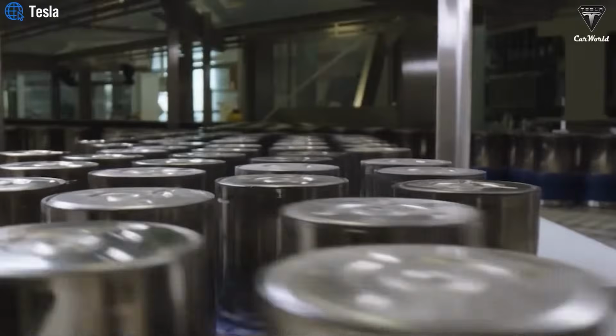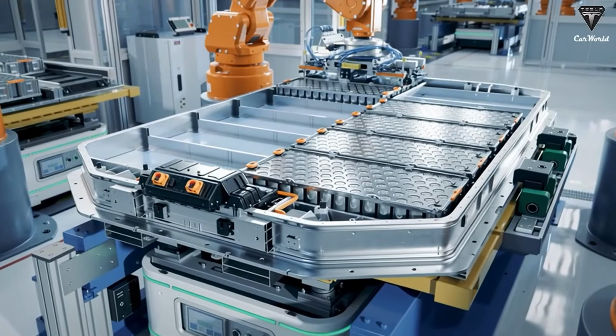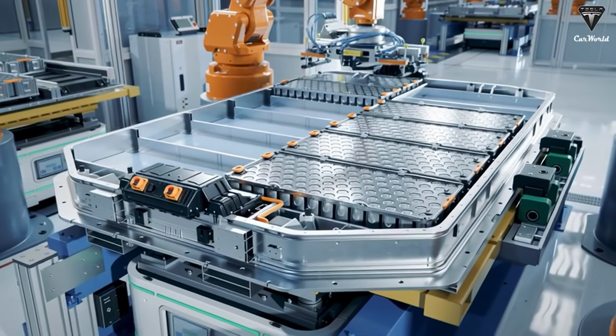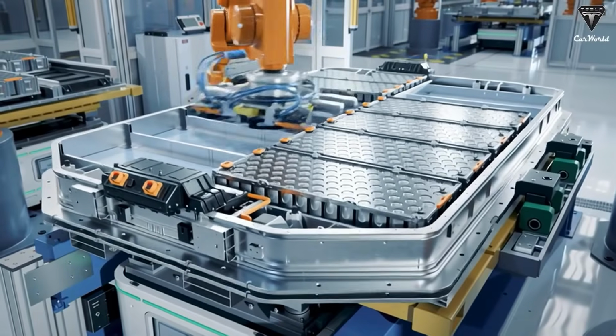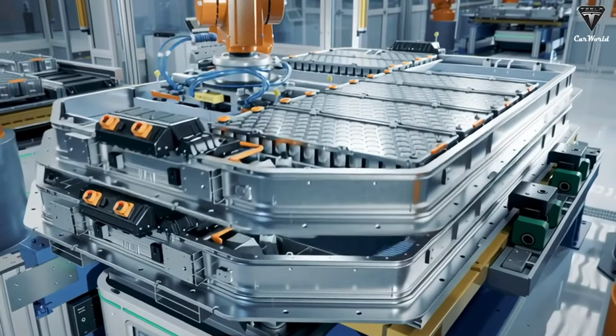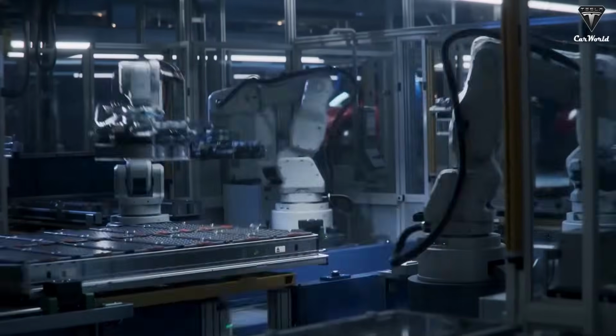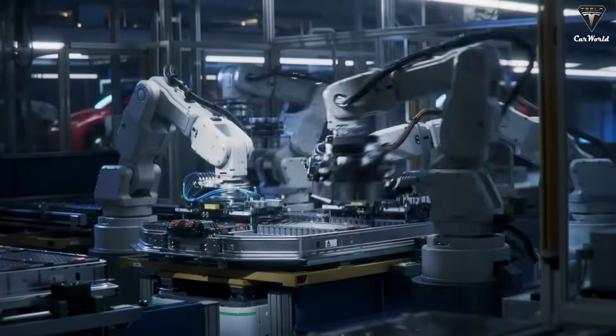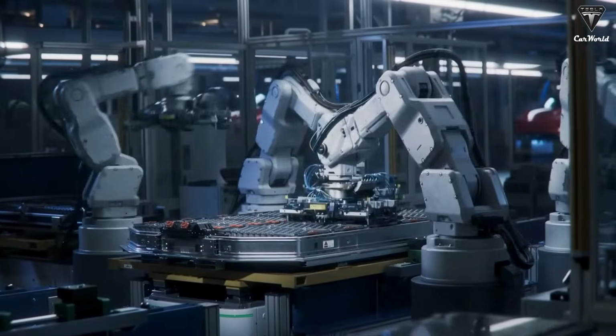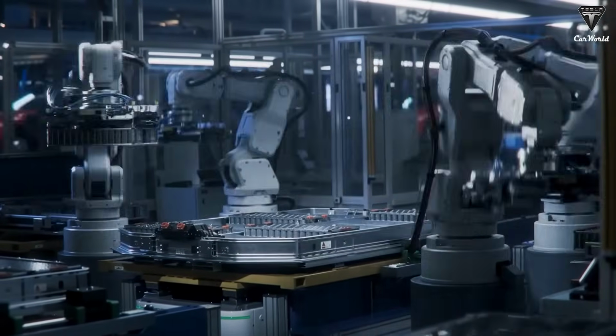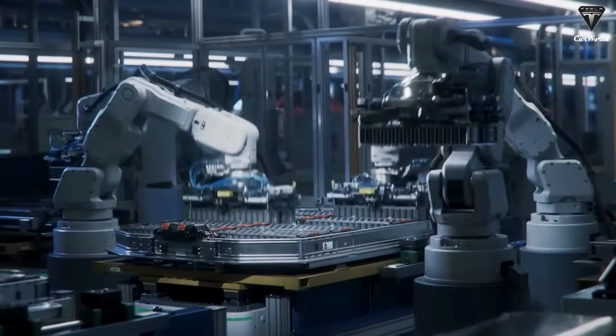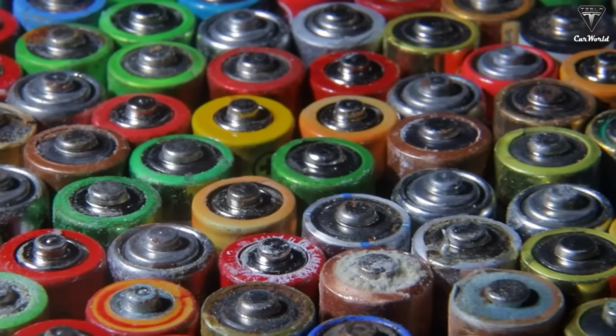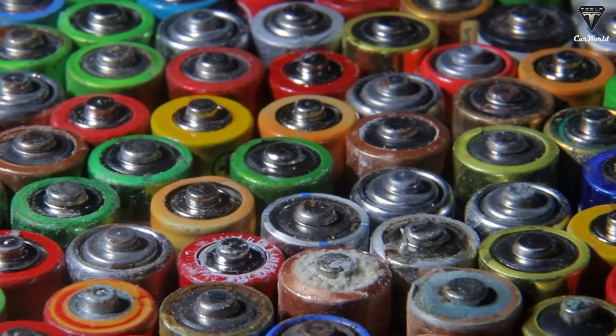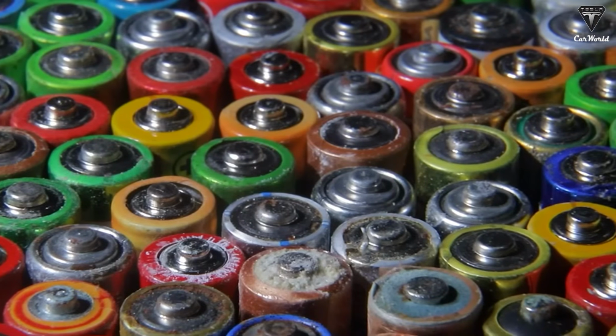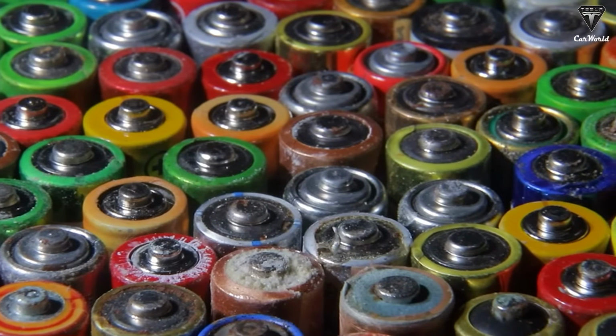As for manufacturing capacity, Farasis Energy has launched a 0.2 gigawatt-hour pilot sulfide battery line in Germany, aiming to scale up to 1 gigawatt-hour per year by 2026 for both EVs and grid storage. Finally, Huawei has unveiled a hybrid sulfide polymer battery boasting 450 watt-hour per kilogram energy density, over 2,000 kilometers of range, and an 80% charge in just 10 minutes.